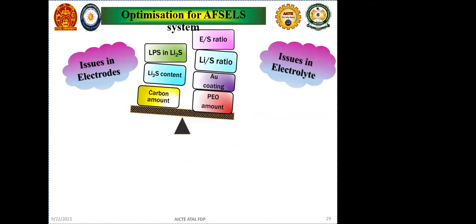Like we have to adjust the LPS and Li2S system. Like as I mentioned, we can use electrolyte in a cathode material, so that the E/S ratio balance will be maintained. And also when we balance the Li2S content, then lithium ionic conductivity and electronic conductivity is also balanced, and then the lithium and sulfur ratio also will be balanced.